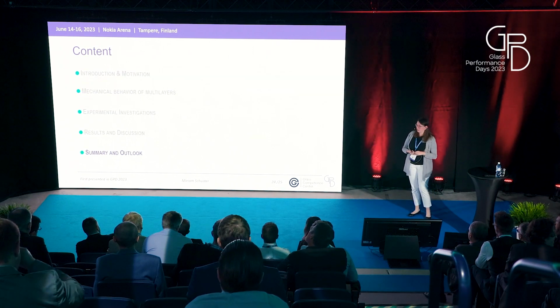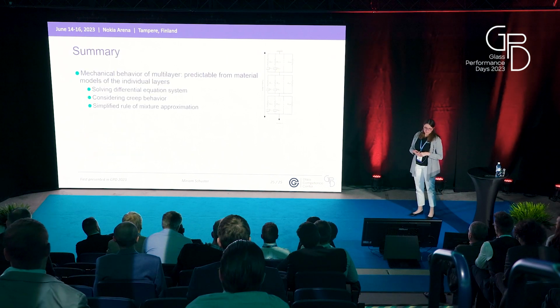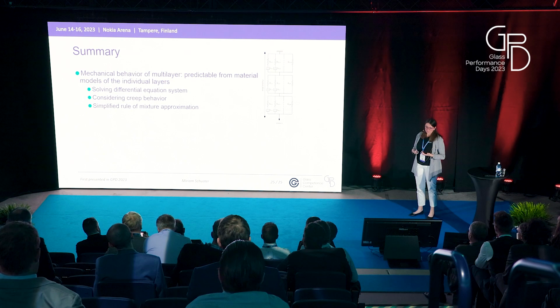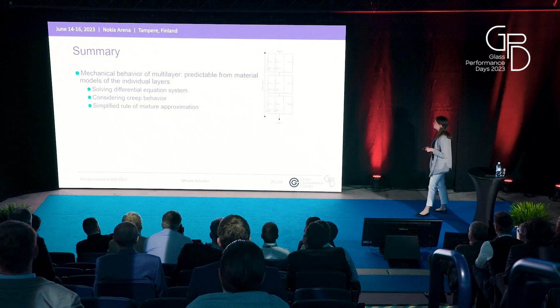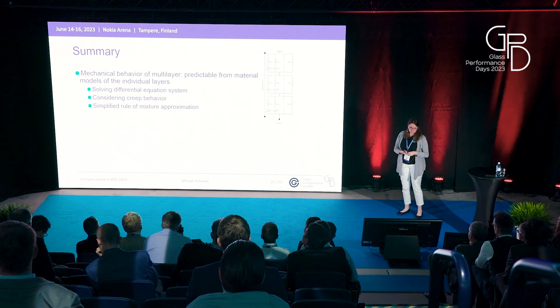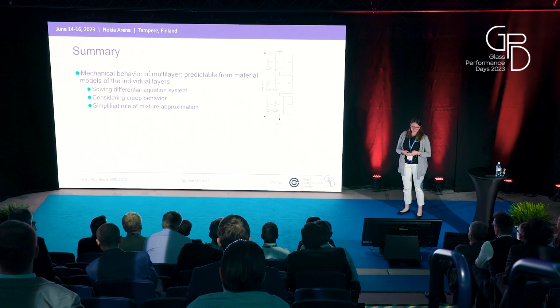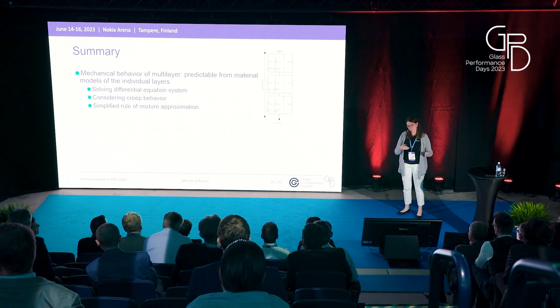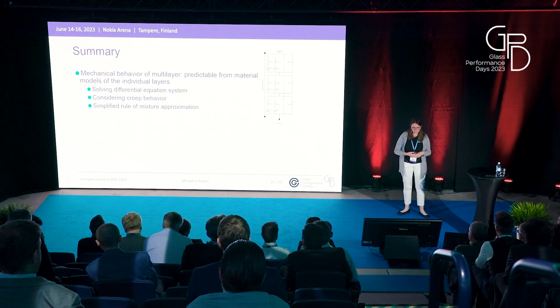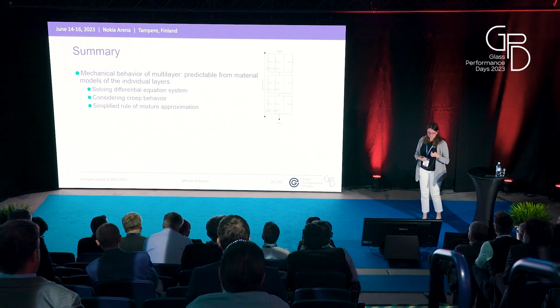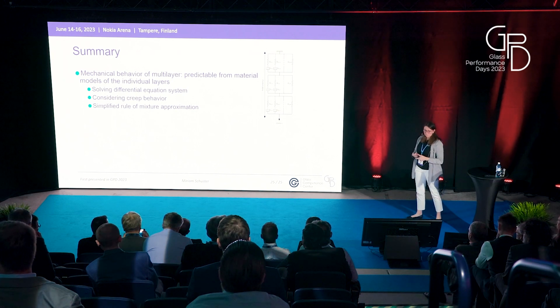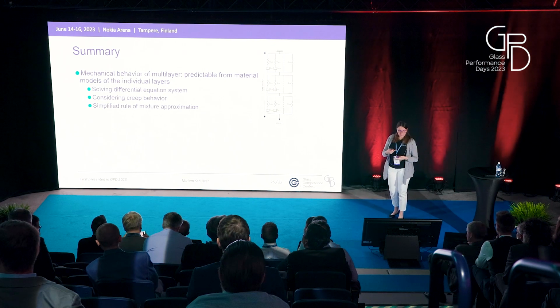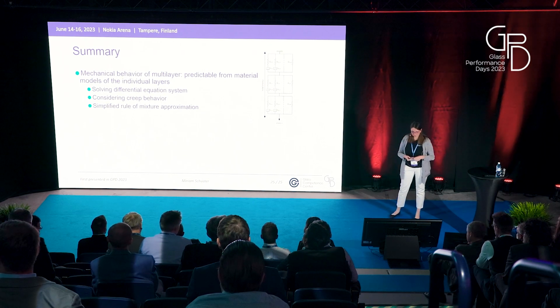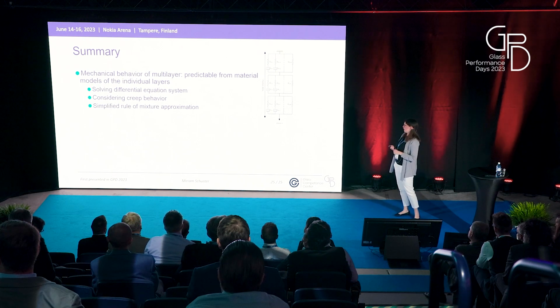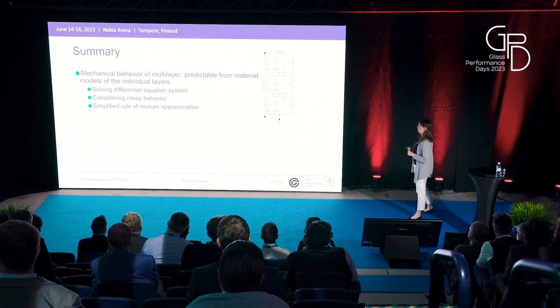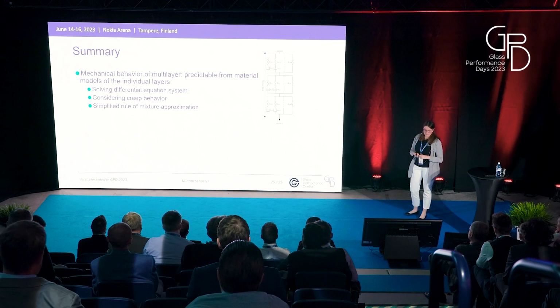So now let's come to the summary and outlook. So we looked at the rheological models of three layers and were able to predict the material behavior of a multilayer from the material properties of the individual layers. We solved the differential equation system. We considered the creep behavior, and we looked at the simplified rule of mixture. And I think, at least for this three layer, the simplified rule of mixture approximation is good enough to predict the material behavior.